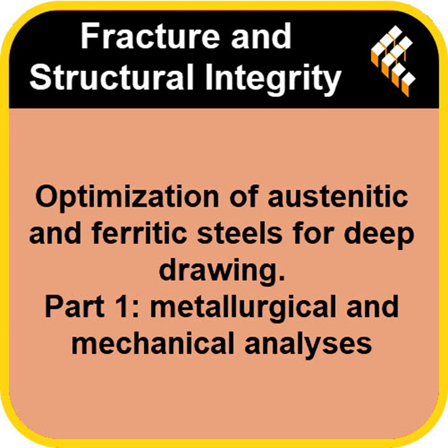Correct. Uniform, maximized deformation. But when the 304 was tested dry, the hardness at the apex was lower. Much lower, up to 100 points lower than in the lubricated test. This confirmed very little stretching actually happened there. Yeah. Instead, the peak hardness shifted down to around zone 7, that area halfway up the wall. Where the localized necking happened. Exactly. It's microscopic proof that the material flow is blocked by friction, leading to premature localized failure.